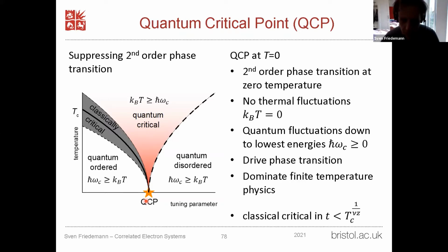So how can we see that quantum fluctuations are important here? Now, let's consider we are in the ordered state here. And on my previous slide, I had the sketch of the material being essentially all magnetized in one direction, or in the sketch, it looked as if the material was black everywhere. If we start there, it's perfectly black. At zero temperature in that simulation, it would indeed be completely black. If we now approach the quantum critical point, there are no thermal fluctuations. So there's nothing which will actually flip small or large patches to the other color and to the other magnetization orientation. And hence, even if you go beyond here, nothing would actually destroy the ordered state, or in other words, melt the order. And you would actually be left with a puzzle. How is the material actually going to convert from perfectly ordered to completely disordered if there are no thermal fluctuations available?